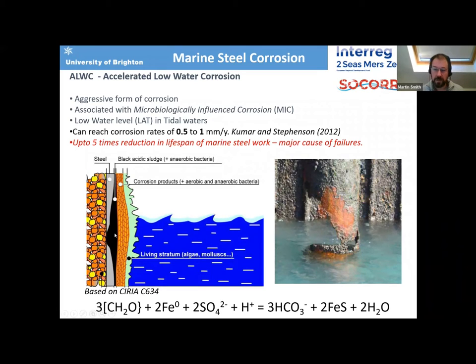What people have determined from previous work, this is a diagram based on a CIRIA manual, is we see a living stratum, macrobiota and microbiota, so mollusks, algae, all sorts of things, colonize the steel. We get a range of corrosion products over the top of that, and protected from the oxic environment, we get a sulfidic sludge, which includes sulfate-reducing bacteria. So people are aware that sulfate-reducing bacteria are involved in this process.